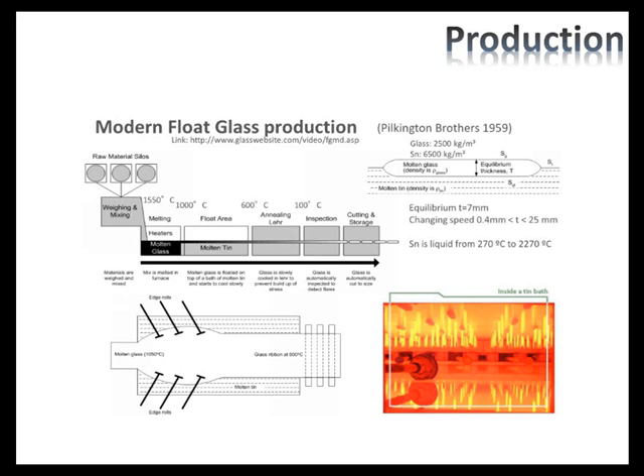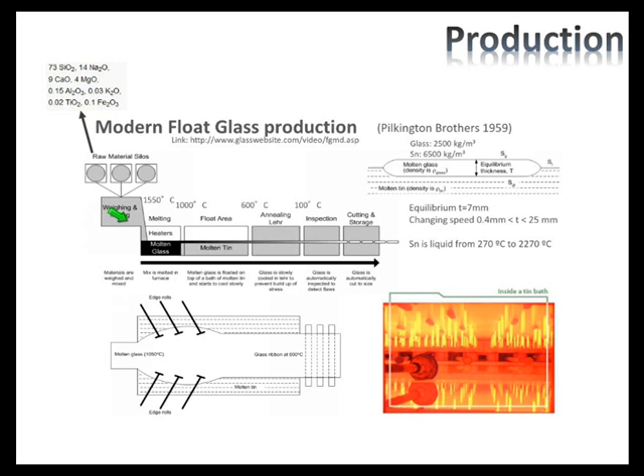The glass production process: glass was first produced in the early part of this era and has been produced in the Middle East for hundreds upon hundreds of years. If we take a collection of all the various materials that we're going to turn into glass — silicon dioxide, disodium oxide, and a number of other things listed here — and heat all of those materials up in a big vat, this is effectively what a modern float glass production line would look like. This methodology was developed in 1959 by the Pilkington brothers. We take all of our raw materials, heat them up, and then pour them out onto a float line.